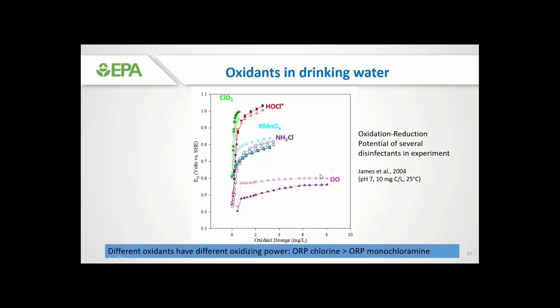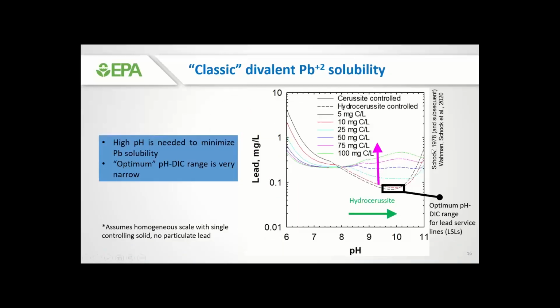But if we assume that we're here in the middle ORP range of this graph, so we're stuck with this divalent lead +2 solubility, let's go back to the solubility diagram and look at that again from a different lens. If we have a system with lead service lines, and we base our understanding on this theoretical solubility modeling calculations, we really would need a very high pH to minimize lead solubility. To be at the absolute lowest point in these curves, we would actually need to be forming hydrocerussite as the controlling solid, so therefore we would need fairly high pH, and we would need pretty low DIC as well.